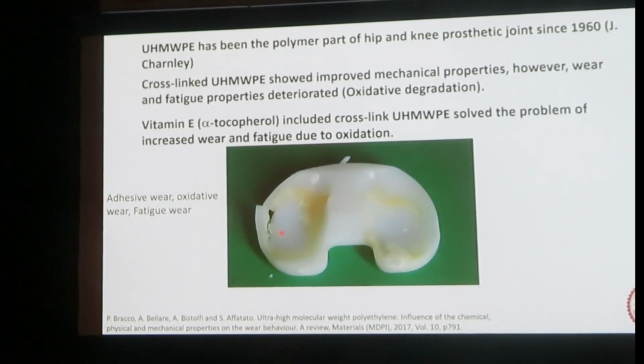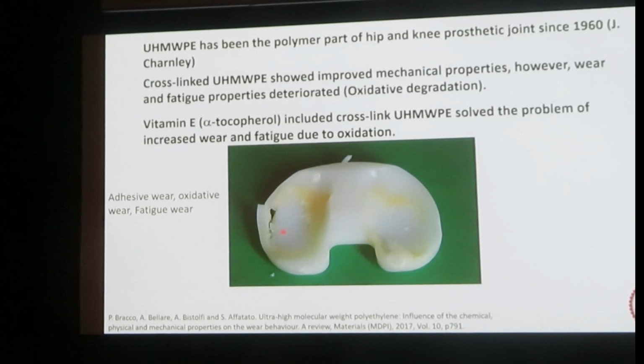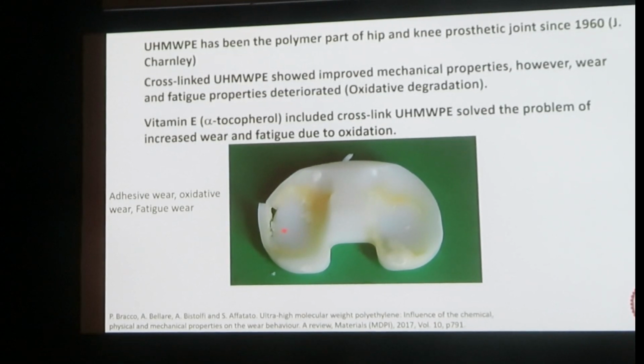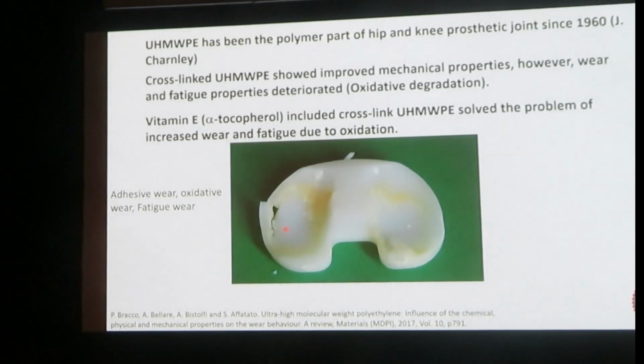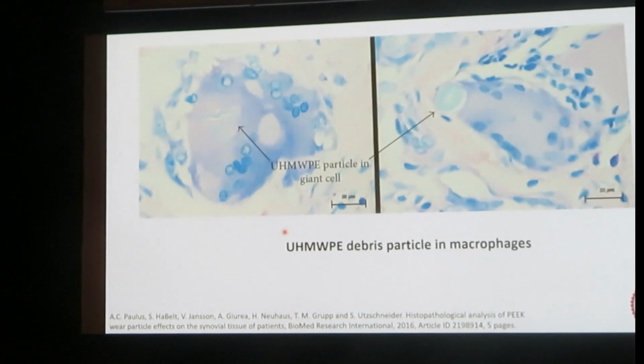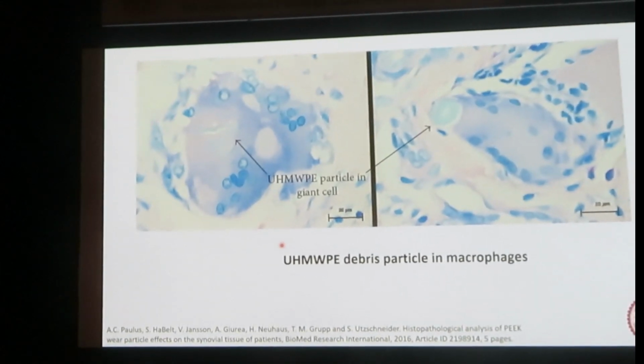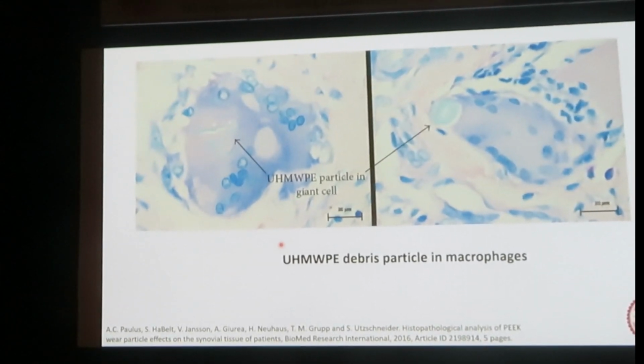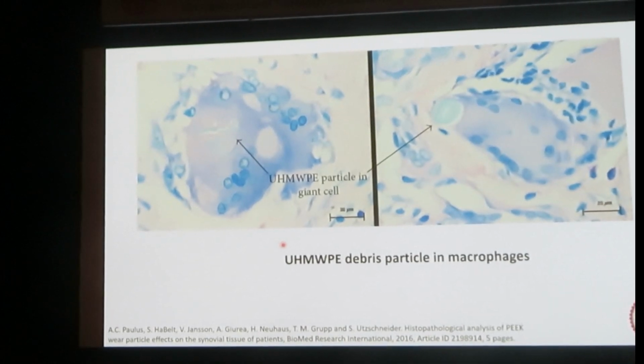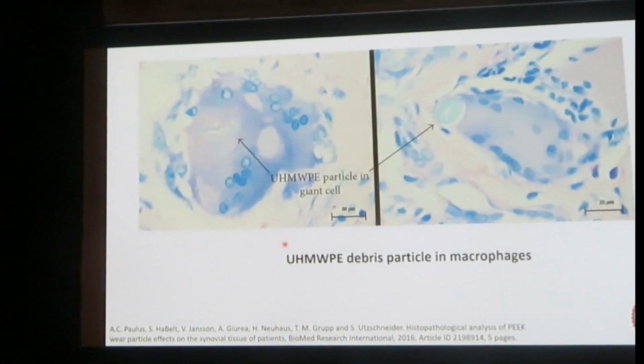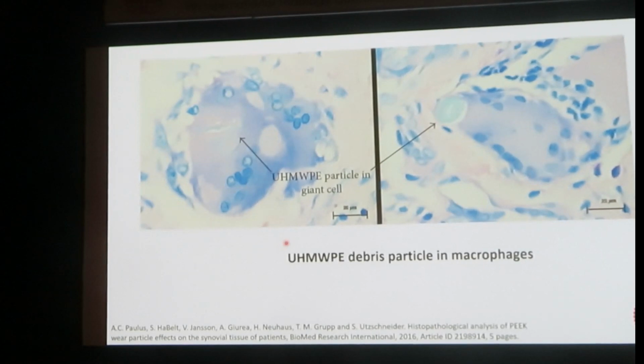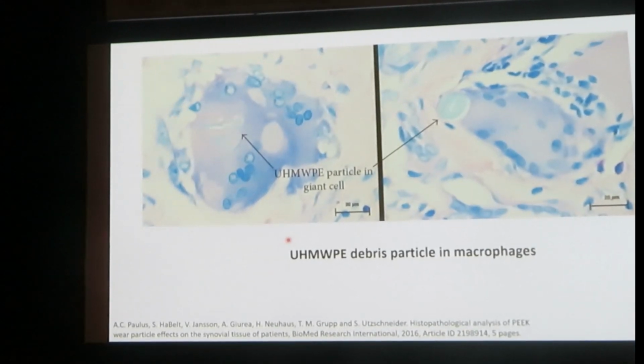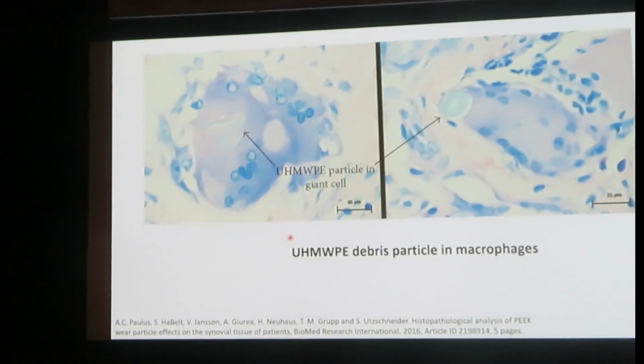And the wear will lead to wear particle formation, and the wear particles will migrate from the joint to some other parts. It has been found that UHMWPE debris particles can be eaten up by macrophages, and this can create other issues in the patient. So all focus is to reduce the number of particles in the joint as much as possible.